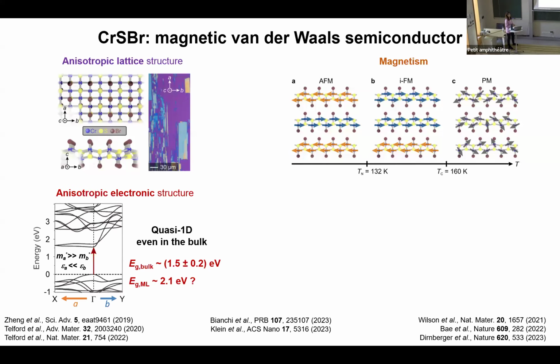Now comes the surprise of chromium sulfide bromide. The calculated theoretical band structure shows that the conduction band is very flat along the gamma X direction, which is associated with momentum along the A crystallographic axis. However, we have a relatively dispersed parabolic conduction band along the gamma Y direction, associated with momentum along the B direction. So this highly anisotropic electronic structure gives rise to a very anisotropic dielectric function of chromium sulfide bromide, together with effective mass of the electron along the A and B directions. So the electrons behave more or less as quasi one-dimensional in chromium sulfide bromide.